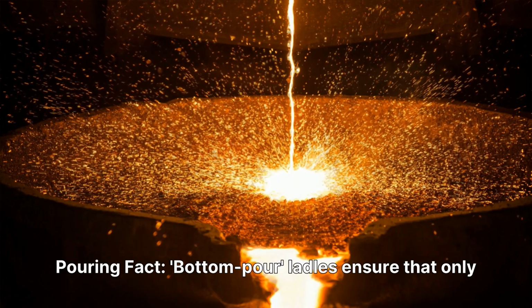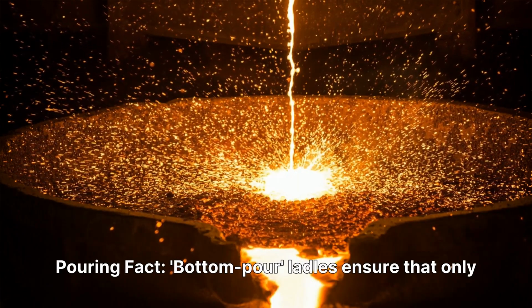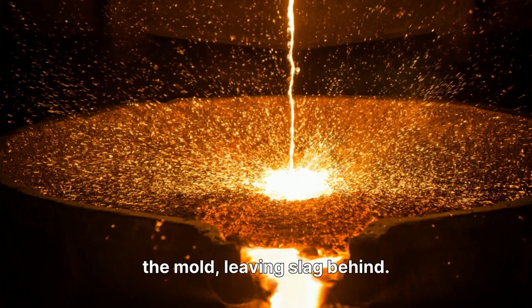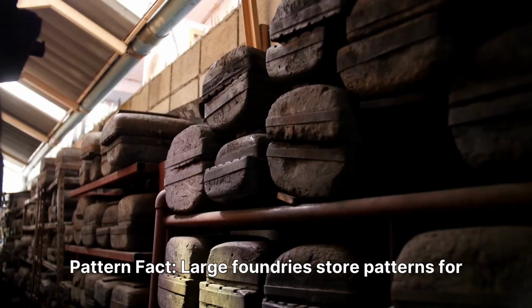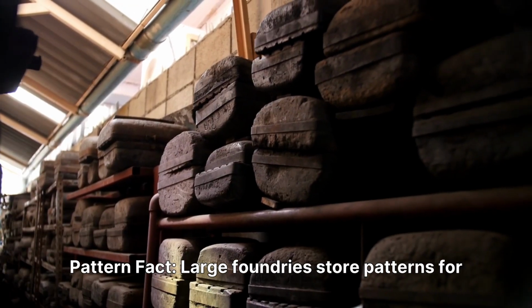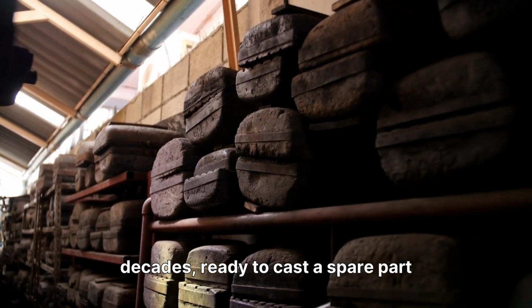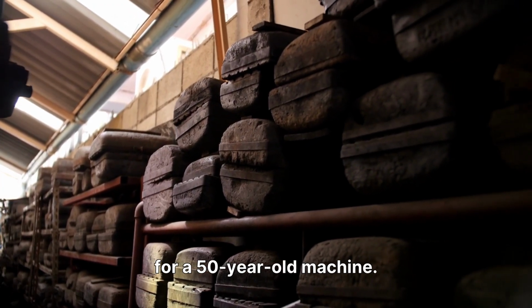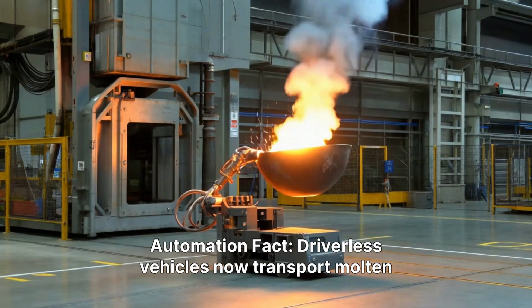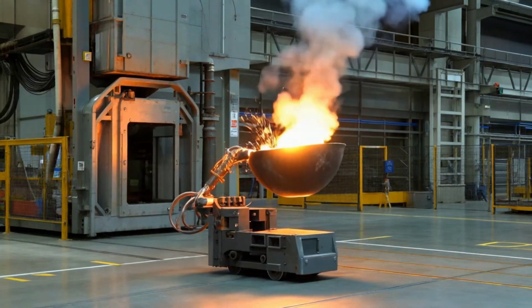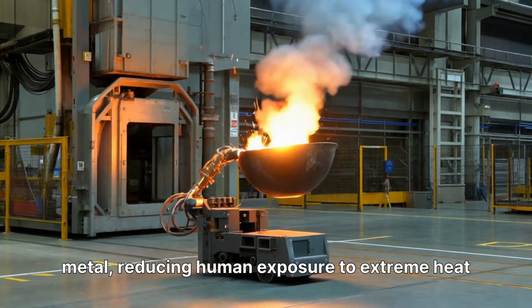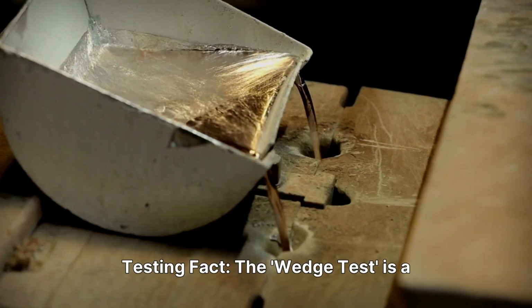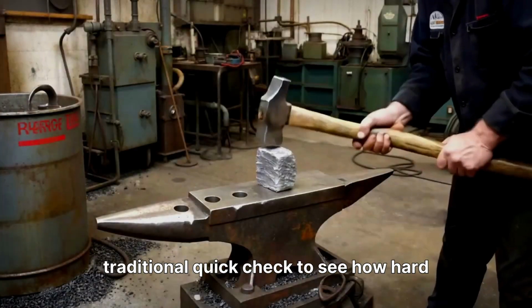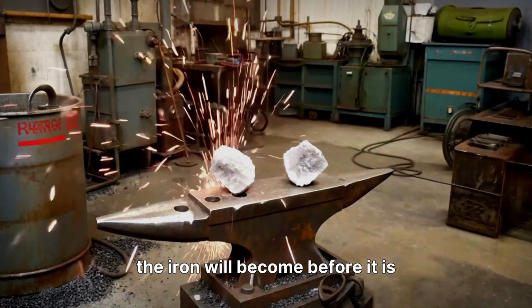Pouring fact. Bottom pour ladles ensure that only the purest iron at the bottom enters the mold, leaving slag behind. Pattern fact. Large foundries store patterns for decades, ready to cast a spare part for a 50-year-old machine. Automation fact. Driverless vehicles now transport molten metal, reducing human exposure to extreme heat zones. Testing fact. The wedge test is a traditional quick check to see how hard the iron will become before it